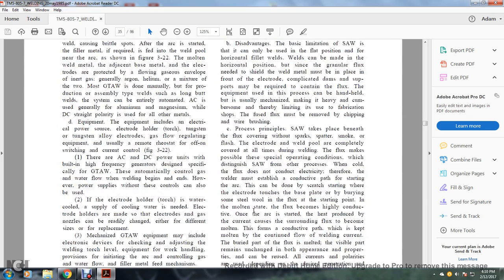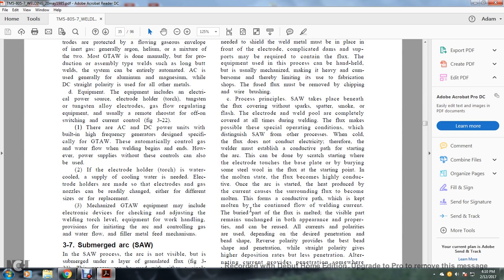Alright, process principles. Submerged arc welding takes place beneath the flux without the spark and the spatter, the smoke, and the flash. The electrode and the welding pool are completely covered at all times during the weld. The flux makes possible these special operating conditions which distinguish submerged arc welding from other processes. The cold flux does not conduct electricity, therefore the welder must establish a conductive path at the starting of the arc. This can be done by a scratch start, where the electrode touches the base plate, or by placing some steel wool and flux as a starting point.